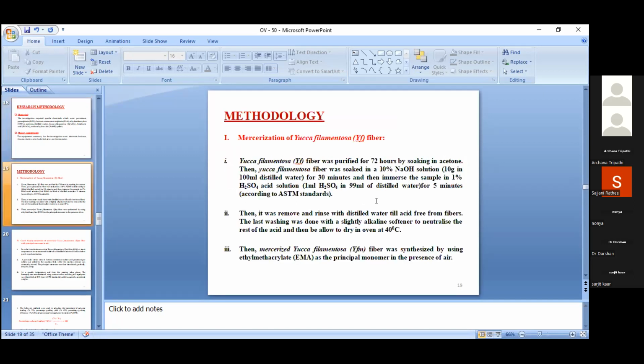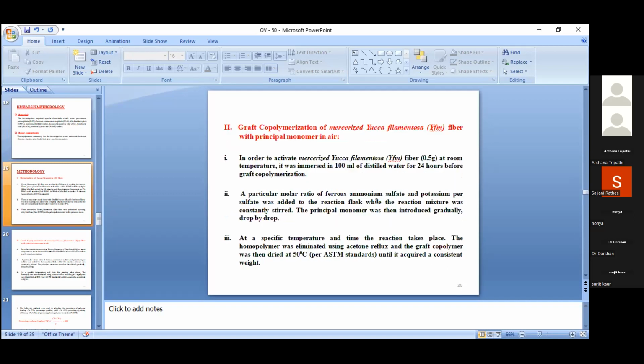Research methodology. Mercerization of yucca fiber. Yucca fiber was first purified for 72 hours by soaking in acetone. Then yucca fiber was soaked in 10% sodium hydroxide solution for 30 minutes, and then the sample was immersed in 1% sulfuric acid solution for 5 minutes. Then it was removed and rinsed with distilled water till the fibers were acid free. The last washing was done with a slightly alkaline softener to neutralize the rest of the acid, and then it was allowed to dry in an oven at 40 degrees Celsius. Then the mercerized yucca filamentosa fiber was used for synthesis with ethyl methacrylate as the principal monomer in the presence of air.